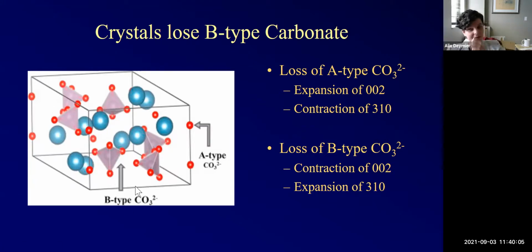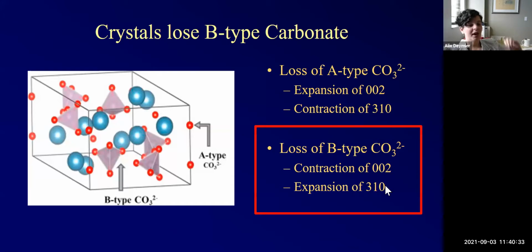Now, obviously, if I'm taking something small out and putting in something big, or taking out something big and putting in something smaller, those are not going to affect the lattice in the same way. So if we lose A-type carbonate, I would expect an expansion of the C-axis and a contraction of the A-axis, which is not what I see. But if I had a loss of B-type carbonate, I should see a contraction of the C-axis and an expansion of the A-axis. So ding, ding, ding, we have lost B-type carbonate.